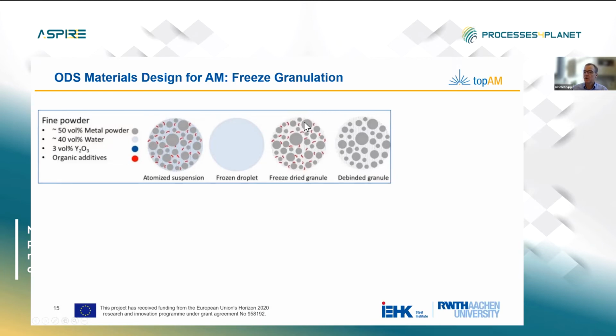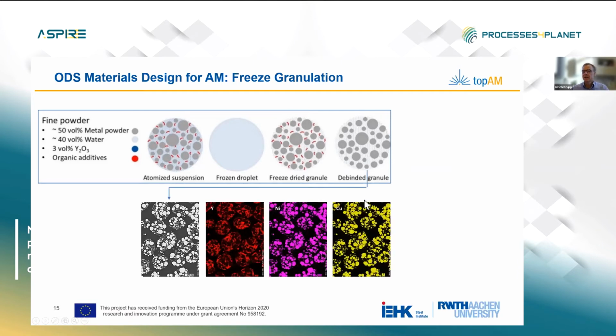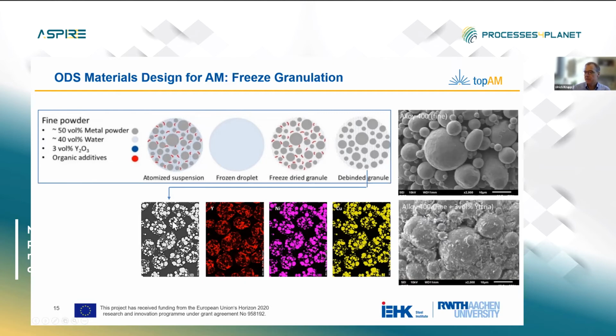So we have the small particles, and inside these are the oxides, and then after debinding, we get printable particles on the scale of about 50 micrometers, and they contain the fine particles and also the oxides. Here, this test was done with 3% yttria. In the same direction, that was a very recent result from last week.